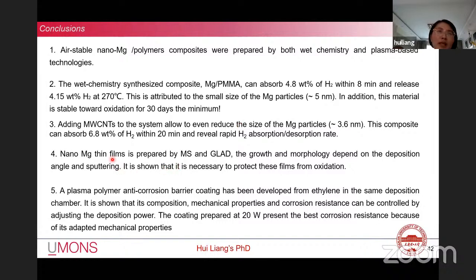The nano Mg film is prepared by magnetron sputtering. The growth and morphology depend on the deposition angle and the sputtering. It shows that it is necessary to protect those Mg films from oxidation. A plasma polymer anti-corrosion barrier coating has been developed from ethylene in the same deposition chamber. It is shown that its composition, mechanical properties, and corrosion resistance can be controlled by adjusting the deposition power. The coating prepared at 20 W power represents the best corrosion resistance because of its adapted mechanical properties.